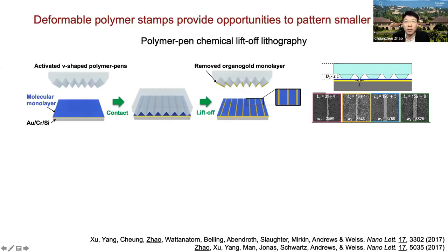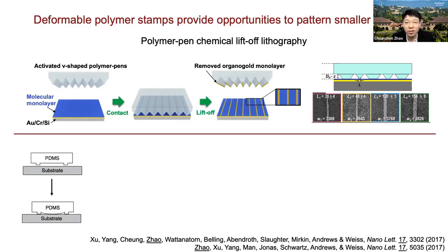We also demonstrated that if you press a probe with different forces, different features can be achieved. If you press them harder, more surface area is going to be in contact, and that will produce a larger feature on the surface. By designing the polymer pen probes and applying different forces, we were able to produce features down to 30 nanometers.